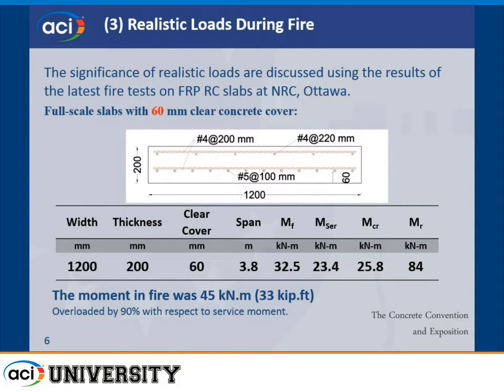Then we come to the question of what loads to use. The standards say to look at the strength of your member and then associate the test load based upon that, generally applying a full service load. This is a case where we have 60 millimeters of clear concrete cover, which is the Canadian standard for FRP reinforcement. It is suggested that that's what you would need for a 2-hour fire rating for FRP.